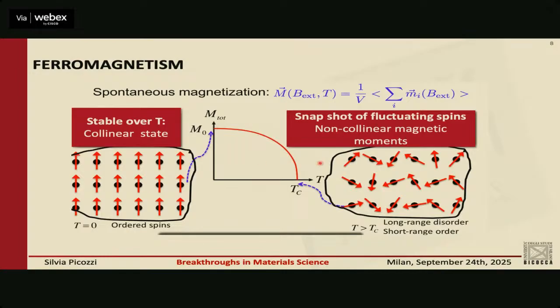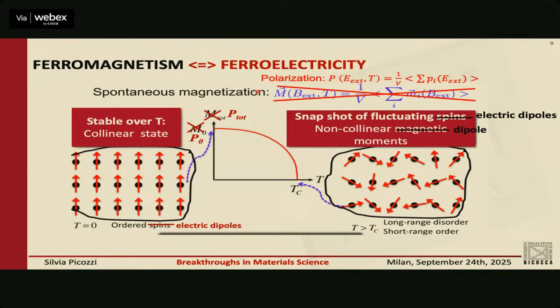my spins order. And so as a result, I get an order parameter, which in the case of ferromagnetic material is magnetization. So you see this order parameter rising below a certain critical temperature. And so you can basically extend this approach to ferroelectrics. So you can just substitute magnetization with polarization. Magnetization is the magnetic moment per volume, and in a ferroelectric you have polarization, which is the electric dipole per volume. So it's a sum average over all the electric dipoles. So instead of ordering of spins, you have ordering of electric dipoles. But other than that, the phenomenology is kind of similar.